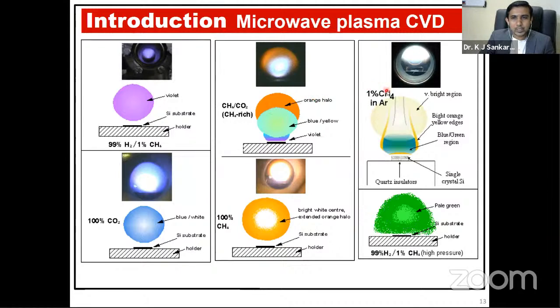And if you use methane and argon, it becomes a brighter greenish region. It's a very big plasma as compared to the hydrogen plasma. When you go with only CO2, it becomes a bluish white. And with only methane, it becomes a bright white center with an extended orange at the corners. So different plasma colors are achieved with different gases, and different plasmas will result in different morphologies of diamond.